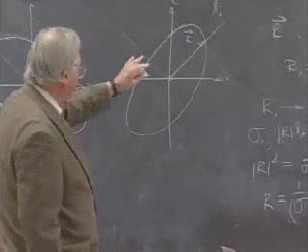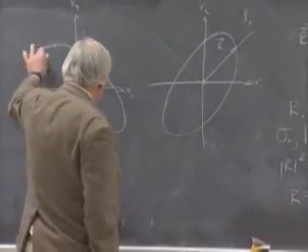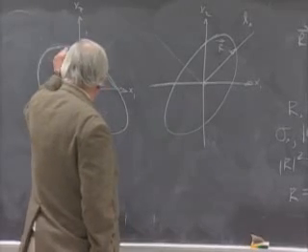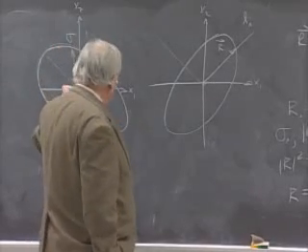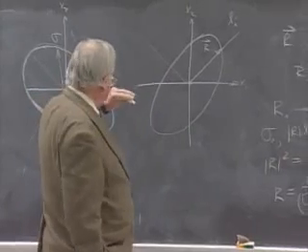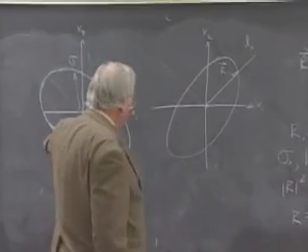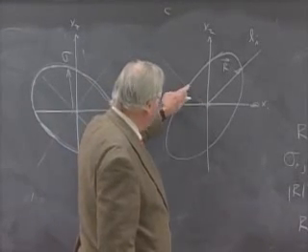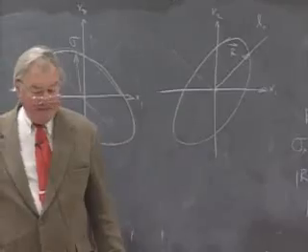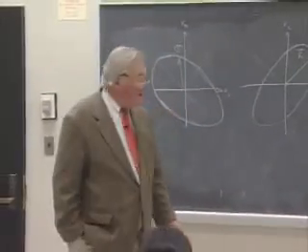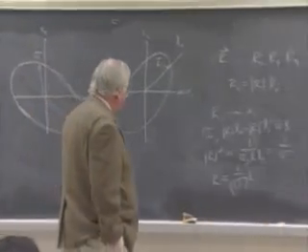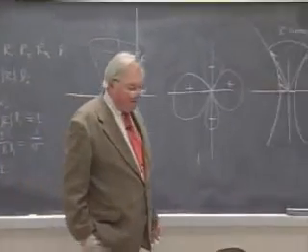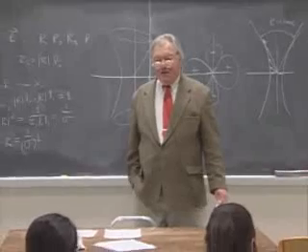For an ellipsoidal quadric, the variation of the property itself with direction is not really ellipsoidal but quasi-ellipsoidal, in that there's a small principal axis, a large principal axis, and the large value of the property goes with the short axis of the quadric. So we have a nice device for representing the value of the property as a function of direction.